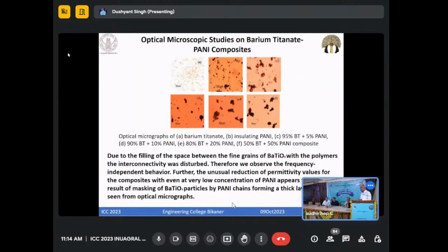We also took this microscopic picture. Simple microscope, nothing like electron microscope. What we could see is that this polyaniline base is making a very thin layer around the particles of barium titanate. Now the barium titanate gives you high value of dielectric constant because of interfacial interaction between the particles. We were able to break this interfacial interaction between the particles, so the basic process which leads to a high value of dielectric constant itself was removed. So once it was removed, you got very low values of dielectric constant.